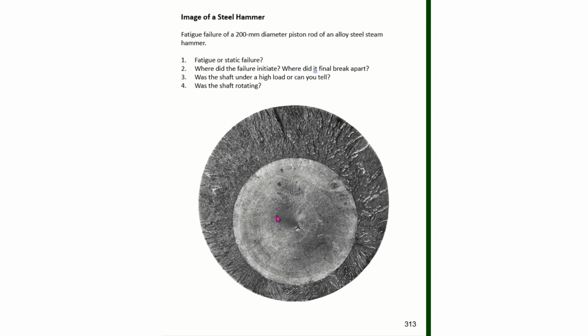In this case, what we had is an axial rod, and we initiated a crack here in the middle. And then as this axial load was applied, this rod propagated a crack radially out in this direction, and then you can see here that we had the final brittle fracture. Compared to the previous example, the applied load is a lot bigger in this case because we have a lot more area here that experienced brittle fracture compared to the fatigue surface.